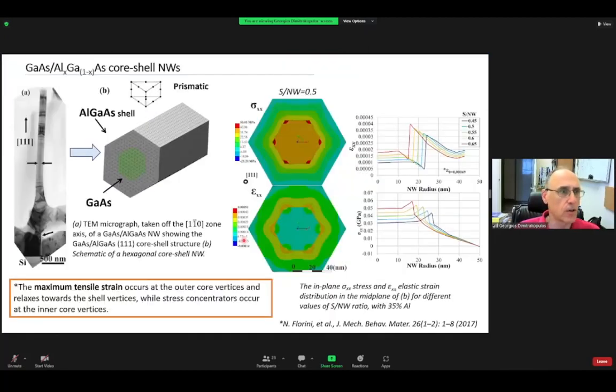So this is also an example from cross sections of core-shell nanowires, and this kind of analysis gives you the additional advantage that you can use Cartesian coordinates, or you can use cylindrical coordinates. Here, this is in cylindrical coordinates, and you can see very nice images of the strain field, like kaleidoscopic images of strain fields. And you can be quantitative with very high accuracy.